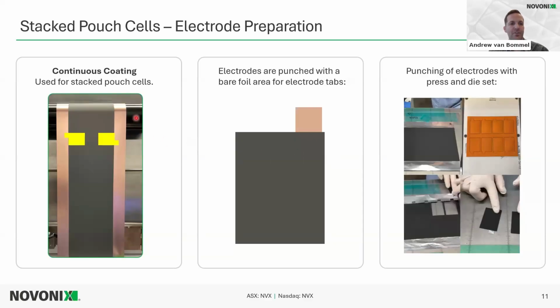To prepare these electrodes, continuous coating is used. So for the slot die coating, we can coat intermittent or patch coating, but we could also do a simpler continuous coating. So this is used for stacked pouch cells, and you can see this continuous coating, there's margins, areas where there's no coating. So that's where the tab gets welded. They're just indicated by those yellow punches there.